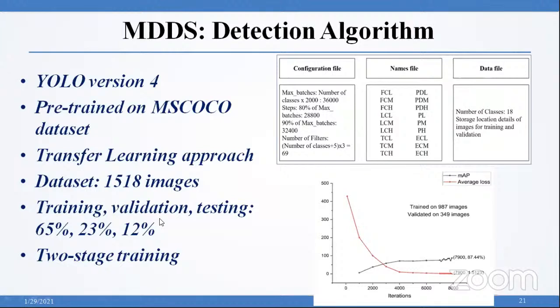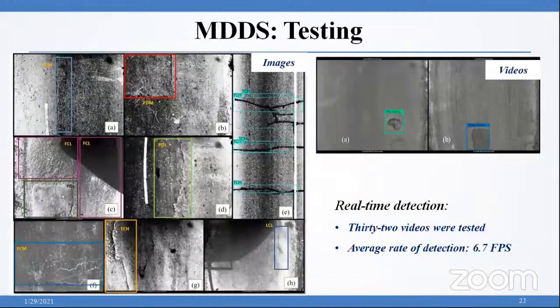At the end of 7900 iterations, the MDDS achieved a precision of 87.44% and an average loss of 1.5123, which was quite promising compared to the results reported in the literature. Then various images were tested on the MDDS, and the performance was recorded.